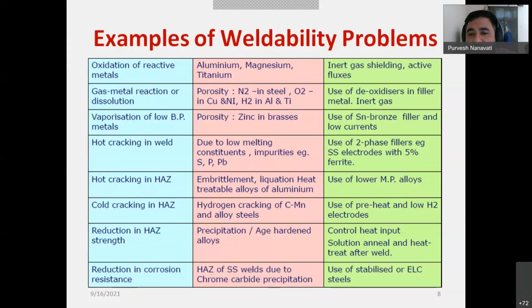And hot cracking in weld, as I mentioned, is due to low melting constituents and impurities of alloy elements like sulfur, phosphorus, lead in the weld metal. These low melting impurities are segregated into the grain boundary. They form a liquid film. So under the cooling stresses, there will be separation of the grains at the grain boundary, and you have cracking. So you have to use two-phase filler metal, SS electrode with a sufficient amount of ferrite, and there will be hot cracking in the heat affected zone.